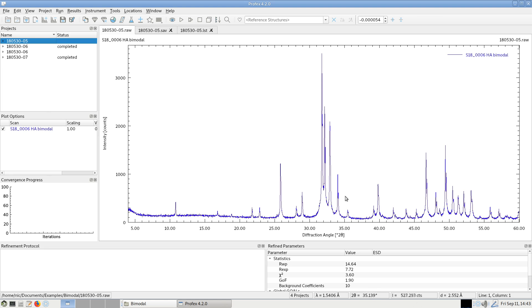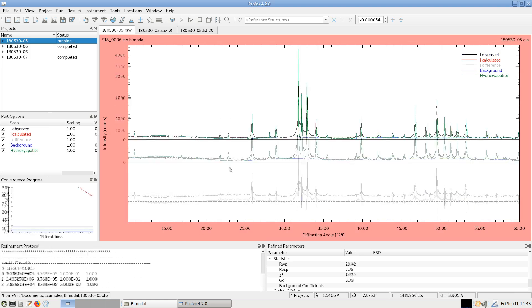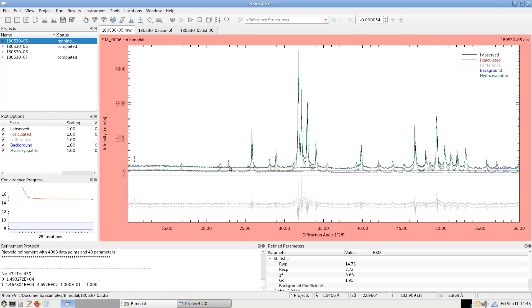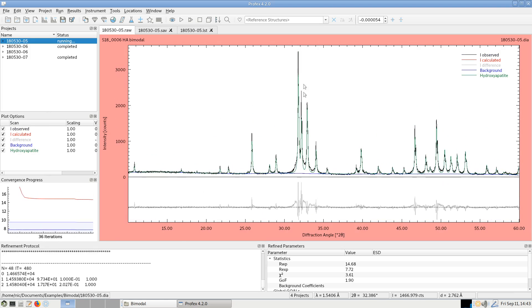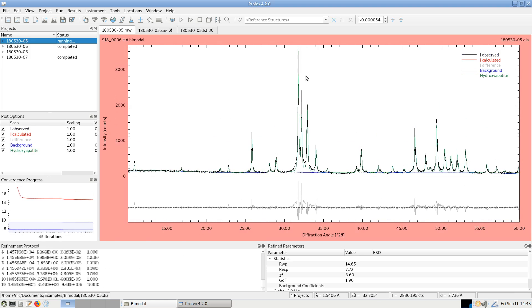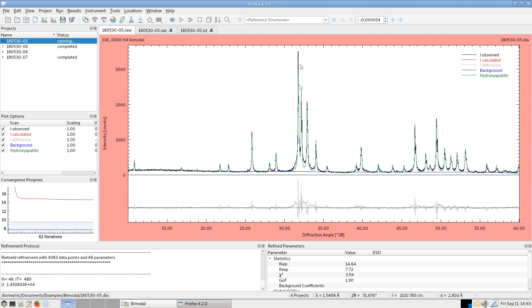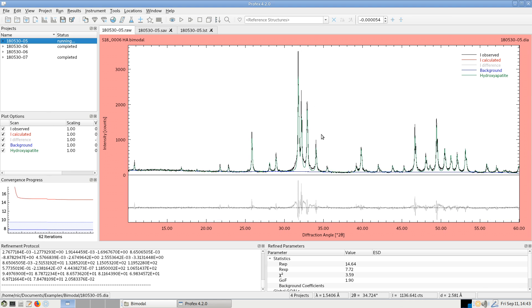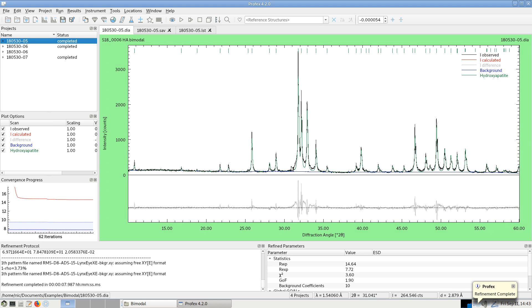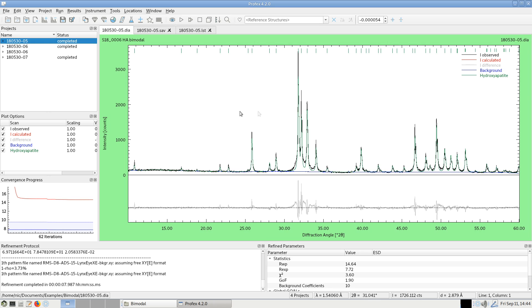And if we try to refine this sample, we will not get a good fit because the peak shape functions are not able to describe this distorted peak shape with the broad feet with just the standard peak shape algorithms. To refine this we have two options.